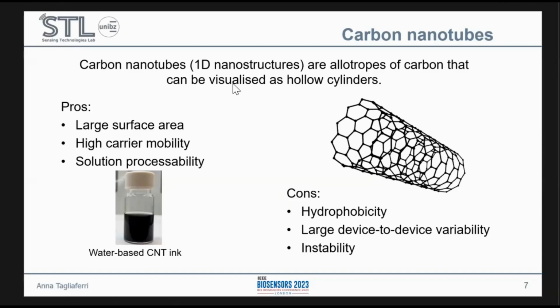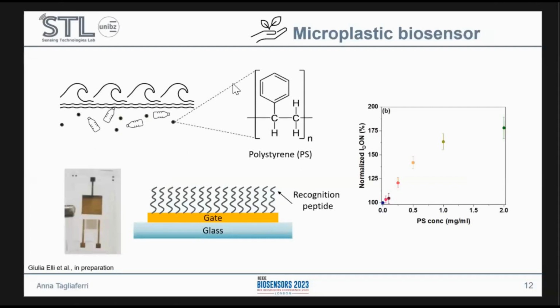So as I was saying, I would like to bring you along our thought process very briefly, and I will show you some of the examples that we have developed already in our laboratory. One of the EG-CNTFETs that we have fabricated is for microplastic detection. In particular, in seawater, we find a great number of polystyrene nano and microparticles. And for this, we have created an electrolyte-gated field effect transistor with a planar configuration, which we fabricated on glass substrate. And we functionalized the gate with a peptide that was found in literature to be selective for polystyrene nanoparticles.